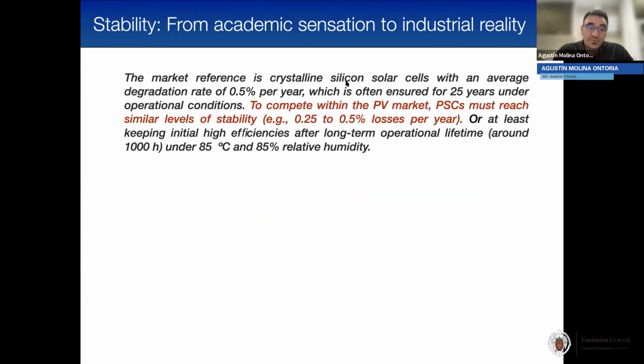For doing that, the market reference is crystalline silicon, which degrades at a rate of 0.5% per year. That ensures 25 years of operational conditions. To compete with silicon, perovskites at least have to be stable, or to be considered for potential commercialization, they should at least keep their initial efficiencies after around 1000 hours at 85 degrees and 85% relative humidity.